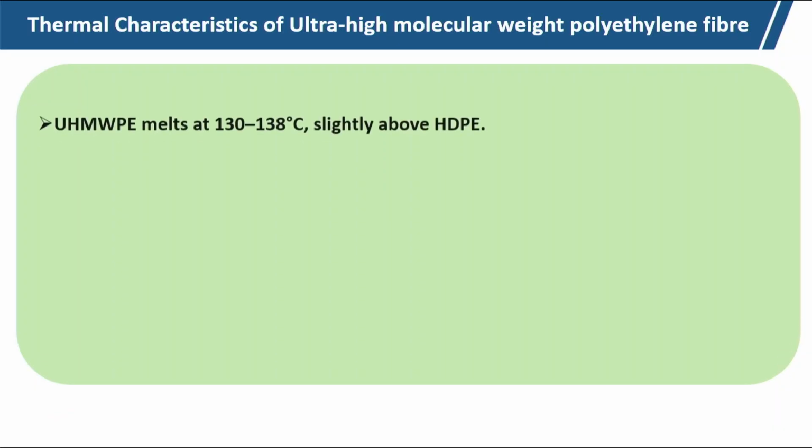Now, thermal characteristics of ultra high molecular weight polyethylene fibers. It basically melts at 130 to 138 degrees Celsius, slightly above HDPE, high density polyethylene.